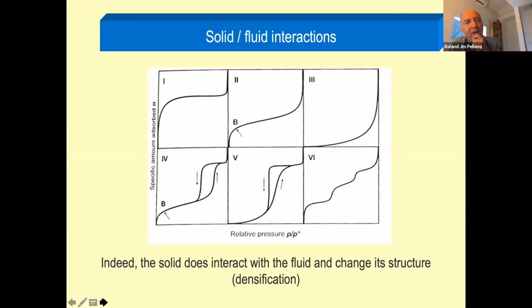Now, what happens if the fluid doesn't like that surface? Then we go to plot number 3. This is typically some kind of fluid that doesn't like the surface—you're not building up this molecular layer. For instance, that could be where water doesn't like some substrate, and in the end, you need to pressurize water to the liquid phase outside, in the bulk, so that eventually you have a condensed fluid somehow in contact with the surface.